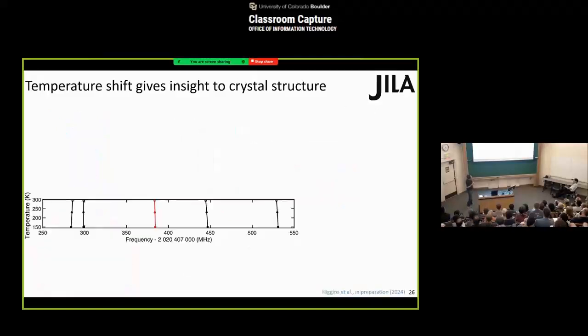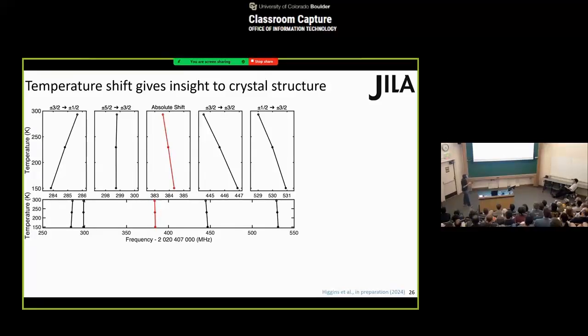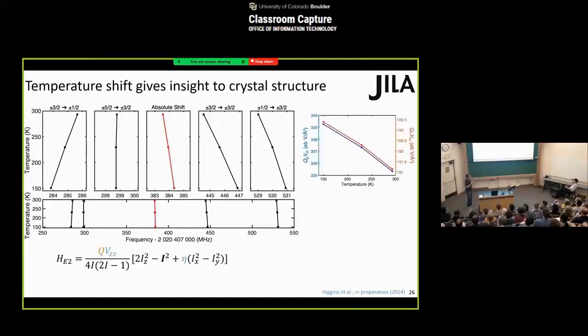So what we did in the experiment is we performed a temperature scan where we changed the crystal temperature by about 150 degrees, and we monitored the transition frequency change. Here I'm showing you a zoomed-in view of the different transition lines, and you can see that their splitting indeed shifts. The red line here is the average frequency, and you can see that the average frequency also moves around with respect to temperature. So again, by fitting back to this Hamiltonian, we can extract the crystal lattice parameters of the crystal. And of course, we know that the nuclear quadrupole moment doesn't change with temperature.